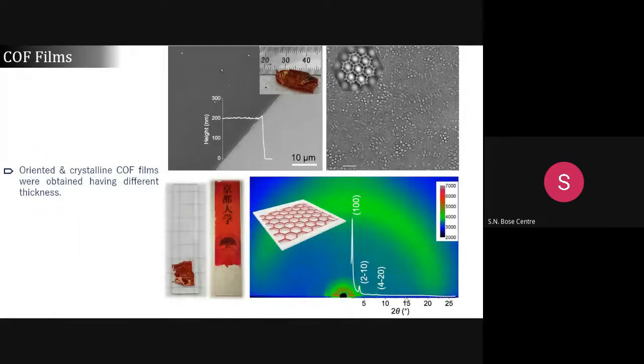Basically, COFs are insoluble powders, which I showed in the initial slide. The powder cannot be processed like any other material. If you take a small molecule, you can create a very good film. But in the case of COF, you cannot do such a thing. It's just a powdery material. So to make the film, you need to use a different kind of method. In this case, you can get a very good film, and you can transfer it over different substrates, or you can grow it on different substrates. And this COF has very good crystallinity, as seen from the GIXRD. And you can clearly see the hexagonal lattice under the cryo-TEM.